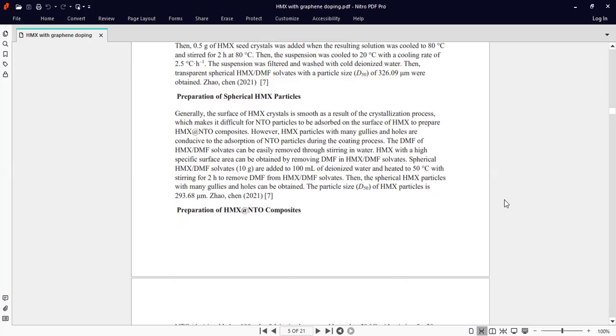Spherical high melting explosive DMF solvates, 10 gram, are added to 100 ml of deionized water and heated to 50 degrees Celsius with stirring for 2 hours to remove DMF from the high melting explosive DMF solvates. Then the spherical high melting explosive particles with many gullies and holes can be obtained. The particle size of HMX is 293.68 micrometer. Now the preparation of HMX NTO composites.